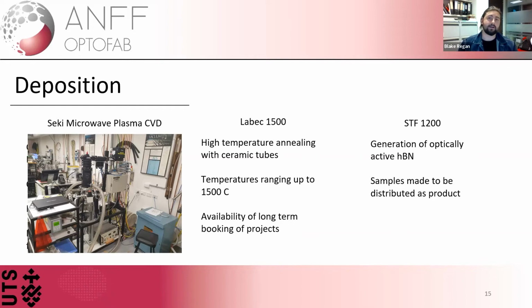It has a very long ramp time of about 5 degrees per minute, I believe it is, which means you'll be spending a number of hours just letting it ramp up, getting to heat, running for as long as you can, and then the same amount of lead time going downwards. This is also a chamber that has access to vacuum compatible systems for if you need to do either annealing in a vacuum or annealing in a specialized environment, where we do have a gas controlled line which can go into the chamber,